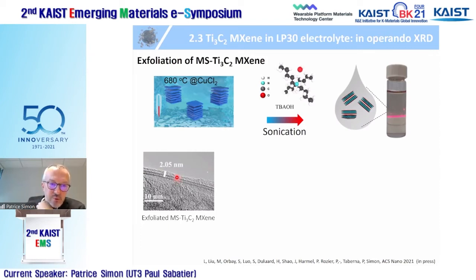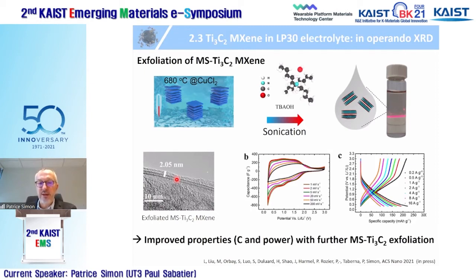Here, this is 2.05 nanometer. It corresponds to, I would say, two layers of MXene. But this is not all the sample that is fully delaminated. Again, you have about 50% of the sample which is really delaminated like that. So it's more difficult to delaminate these materials. But still, when you take this material, as you can see, you still have the same electrochemical signature, symmetry. You increase the capacity and you enhance the power performance.